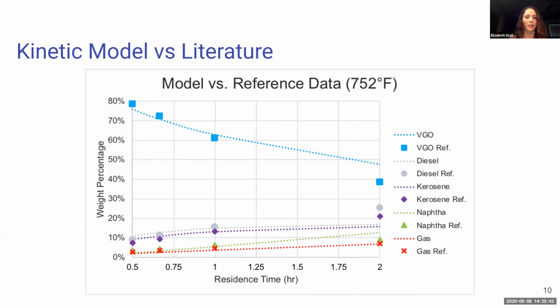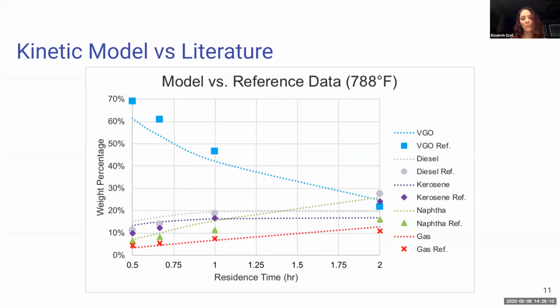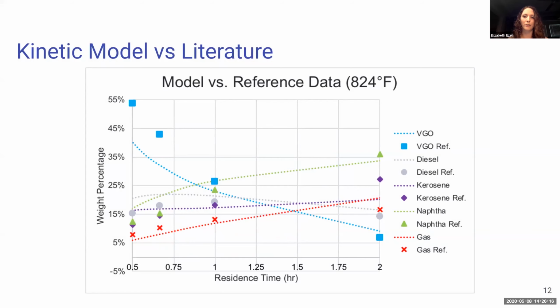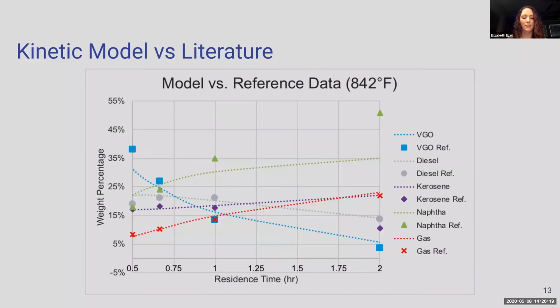And now we have our graphs of our kinetic model versus our reference data. The points on the graph represent our reference data, and the dashed lines represent our model. We modeled 4 different temperatures and 4 different residence times. The residence times were about 30 minutes, 40 minutes, 1 hour, and 2 hours. And the temperatures were 752 degrees Fahrenheit, 788 degrees Fahrenheit, 824 degrees Fahrenheit and 842 degrees Fahrenheit.